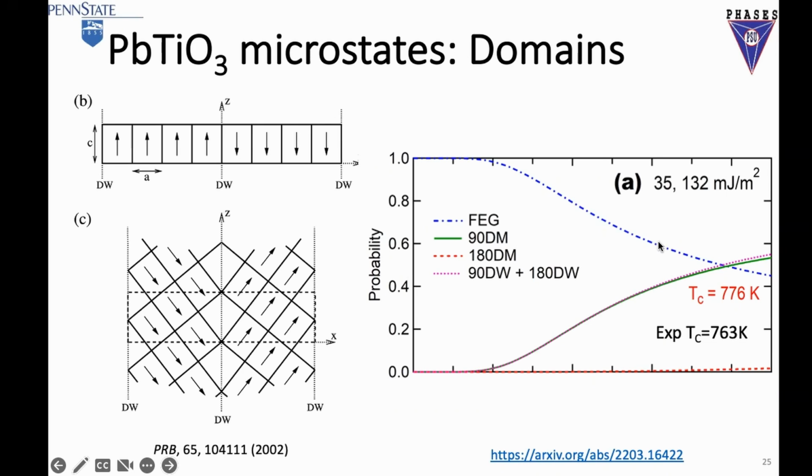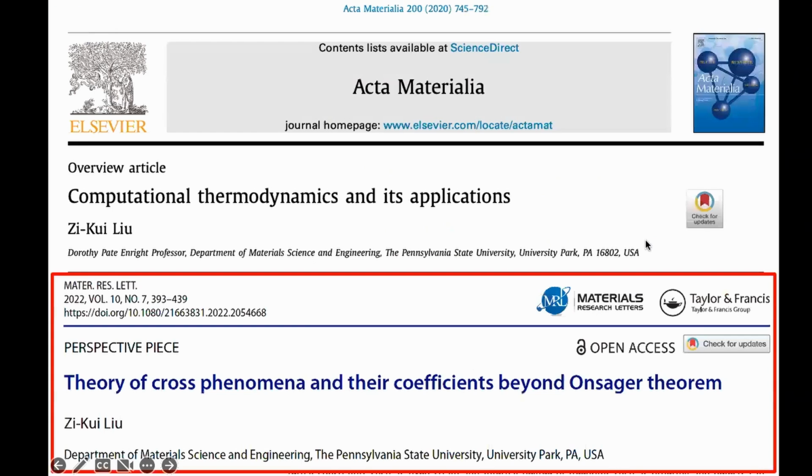We can take his materials and build up these microstates and do DFT calculations in sequence, and predict this transition, for one property. You can actually predict all kinds of properties you can measure, because it's all related to second derivatives of the free energy. The key is to get the free energy. As soon as you get the free energy, you can take derivatives and calculate all the properties you can measure. All right, so I'm finishing my talk. Oh, pretty good, 50 minutes. That's nice.